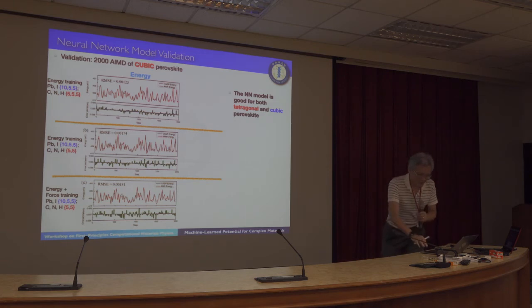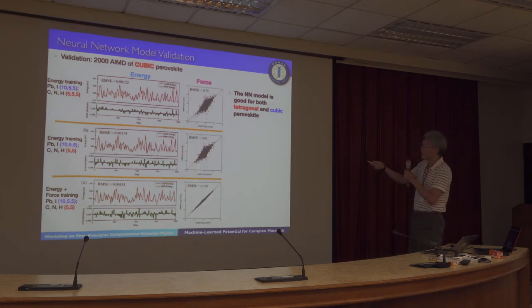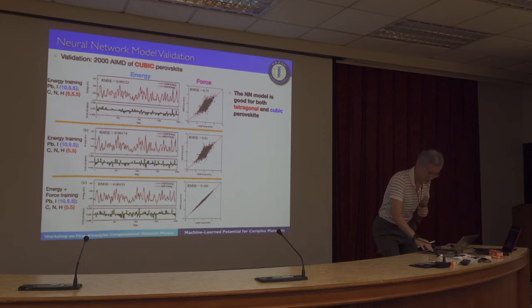But if we look at the force, you can find that for setting 3, which we also put force explicitly as a training target, you can compare the difference in the accuracy in predicting the force. This one, still very good, had a very good correspondence between VASP and the neural network model. However, for this one, training without atomic force, you can see some scattering here.